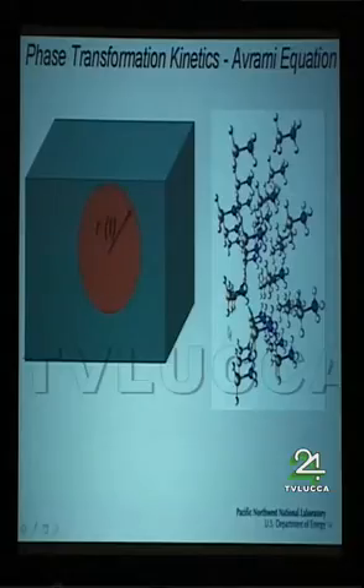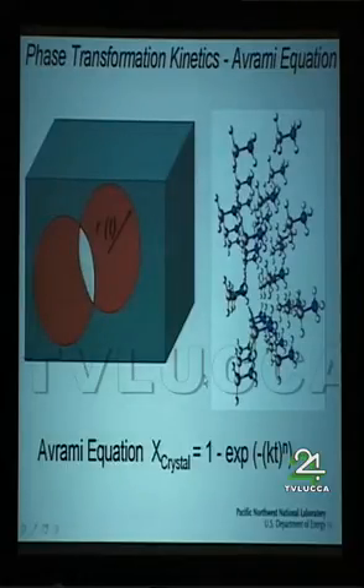And I think, so here's, whoops, I did that too fast. So you get this nucleation site that happens, and it starts to grow. And if you get a nucleation site somewhere else, they overlap. And once they start overlapping, that's when the reaction starts to go down, because you have these depleted areas of hydrogen. And they introduced me to the Avrami equation. The Avrami equation for crystal formation, for crystallization, has both a rate constant in it for the reaction that you can do as a function of temperature, and this exponent here, n, which tells you something about the growth, whether it's 2-dimensional, 3-dimensional type of growth.